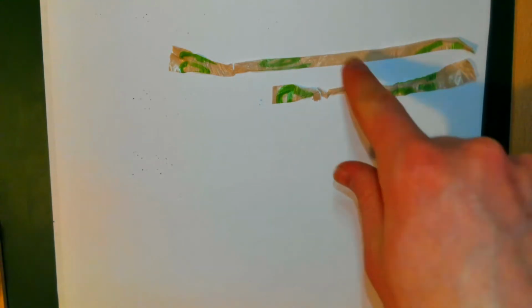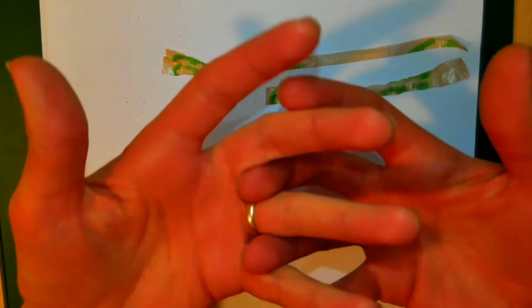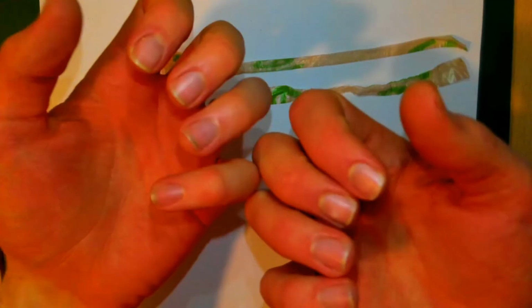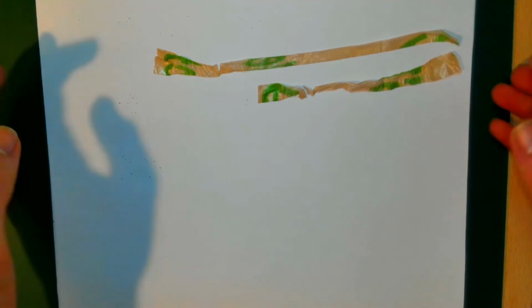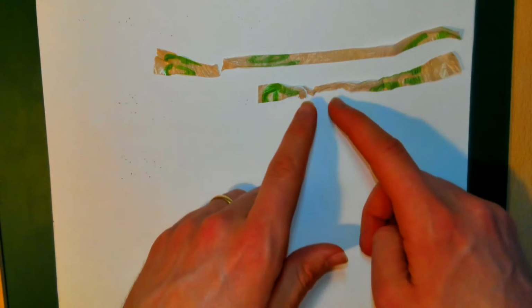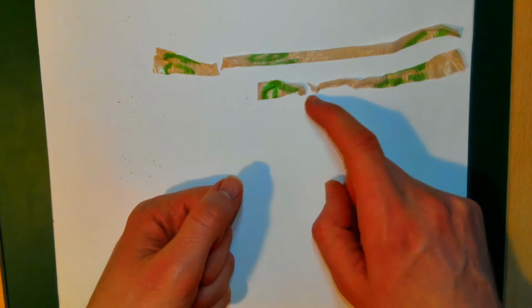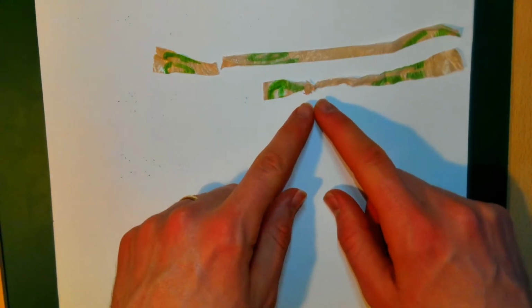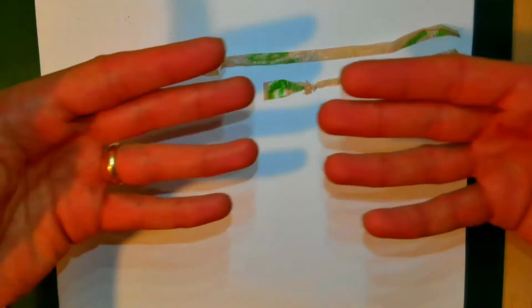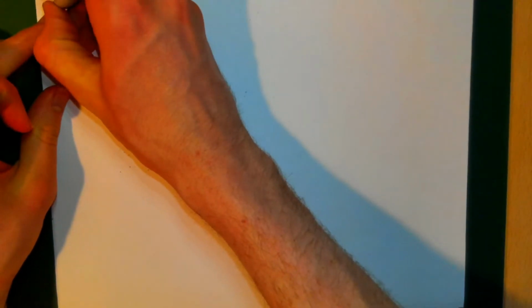Well, depending on the rate at which you deform a polymer, different things are happening at the molecular level, and you end up observing different macroscopic mechanical properties. For example, if we deform things slowly, we might experience a much larger strain before failure. If we deform things quickly, they might appear stiffer for the moment, but they snap before they can fully stretch out and fracture at the very end. So, what's going on here? Well, this phenomenon that we describe here with these two pieces of plastic is what we call viscoelasticity.